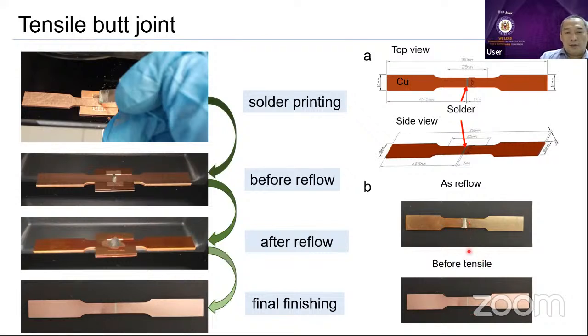Actually, sometimes it's not very nice. We can get a poor joint. So what we can do is polish the surface, right? Polish the surface, and then run the tensile.